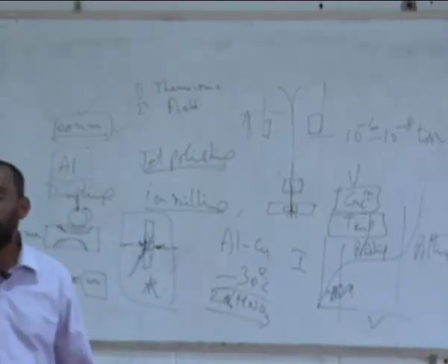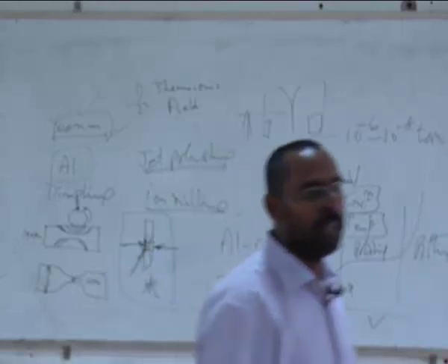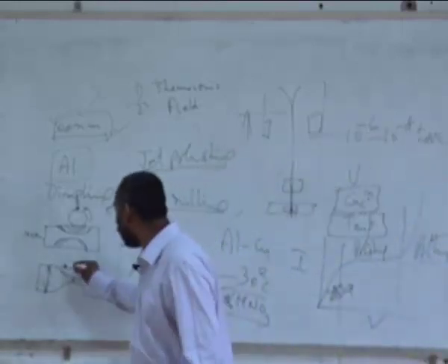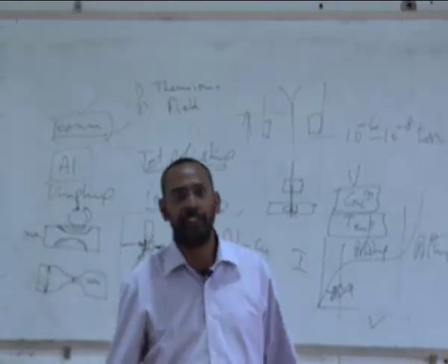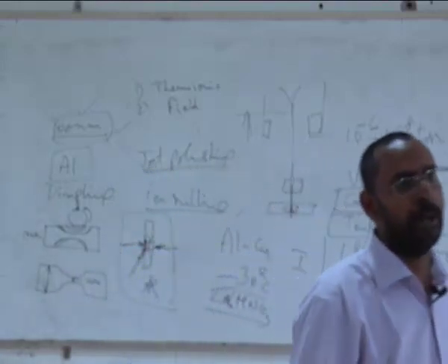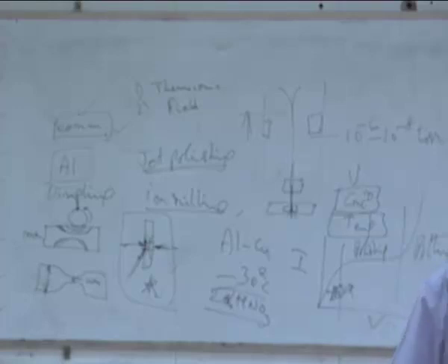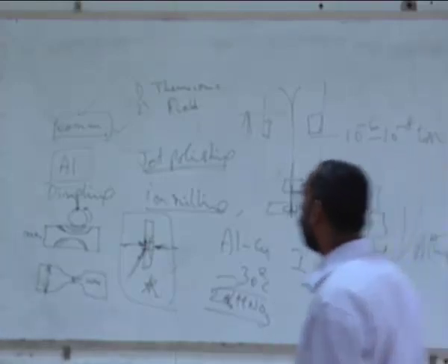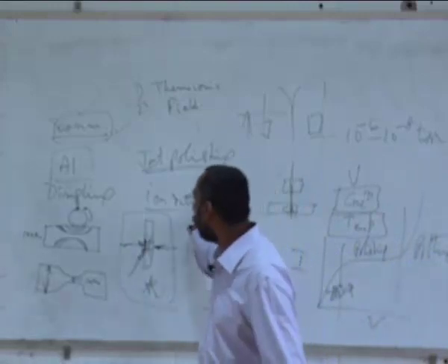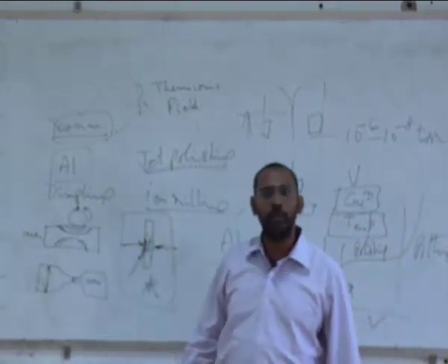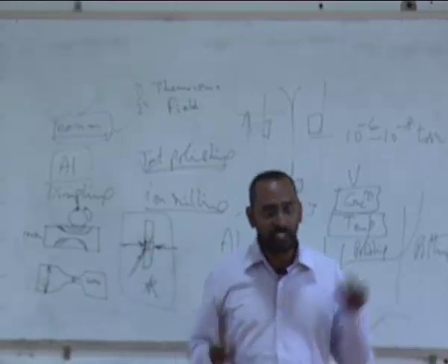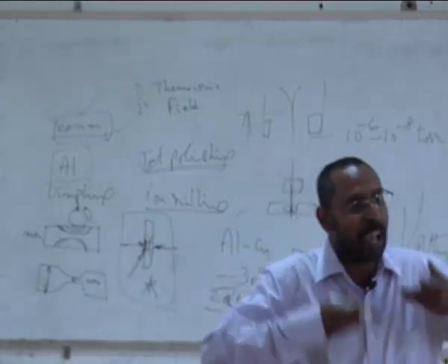And now you put this into an ion mill, so that the amount of material that you need to remove is smaller. And this, we call it dimpling, because this is like a dimple on the cheek. So the term dimpling is used, and we call that machine a dimpler. Okay? So such a process is also used. So before ion milling, we have to do dimpling, but in all this process, you are seeing you are grinding the sample.